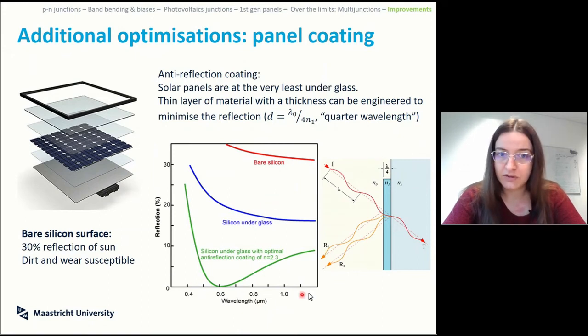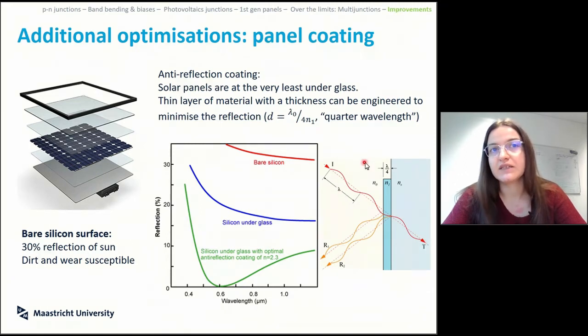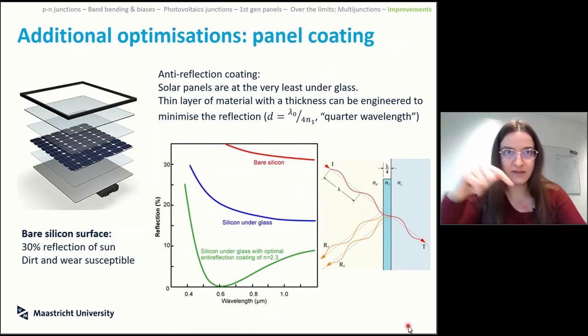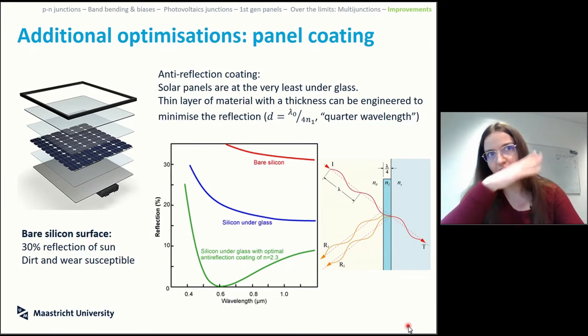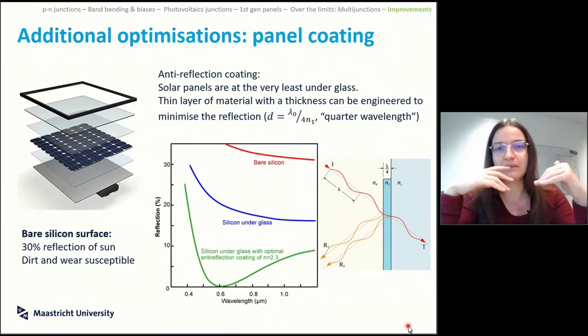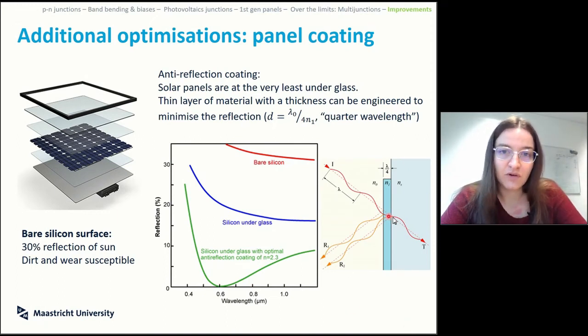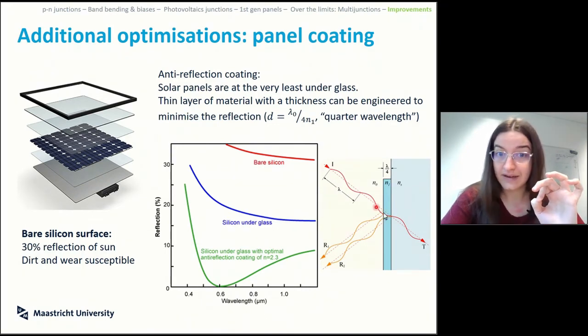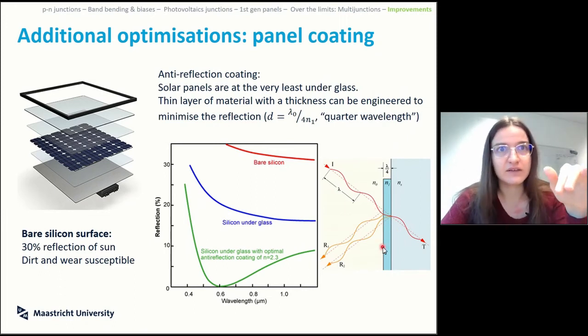If you put an optimal thickness of glass on top of the silicon, you can virtually use all the sunlight that passes through. This is because the quarter wavelength thickness is something that you can optimize to avoid this reflection effect. So there will always be something that gets reflected, but given how reflection works, it's basically a concept of what interference you are letting pass through. If the thickness of your glass is tweaked against the wavelength of the light that you want to pass through, the glass will be perfectly transmitting for that wavelength specifically, and all the others will get reflected off.